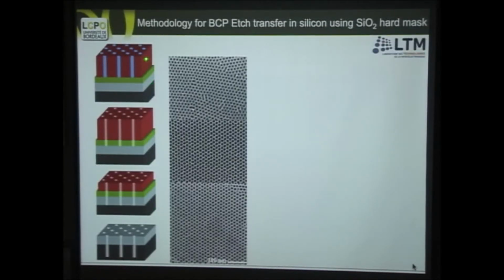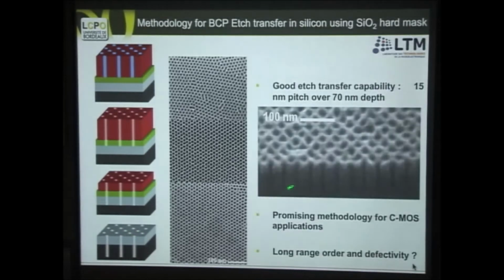Well, the point is that once you have made that, here you see this is the silicon that has to be transferred to this pattern. This is the copolymer that we use to orient the cylinders perpendicular, and this is the silicon oxide, the native oxide layer. Then the process is to remove this block, the blue block, make the holes, and transfer it from a so-called soft mask to a hard mask, which is the silicon, and then change it with a specific plasma and transfer it to the silicon. And that happened, and here is an example that you have features of approximately 15 nanometers pitch with 70 nanometers depth, and they're well oriented.